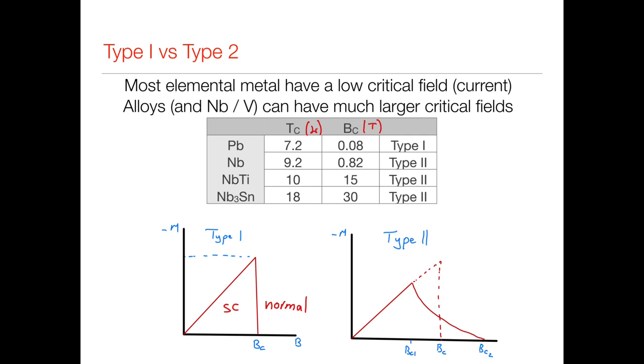The material is still a superconductor because it's still able to pass a current without resistance, but it's not a perfect diamagnet. And the type 2 behavior means that it's able to actually go to much larger fields. So the superconductivity vanishes at this point down here, not this point here. Okay, so type 2 materials can actually have much larger critical fields. And this means they're much more useful in technological applications.